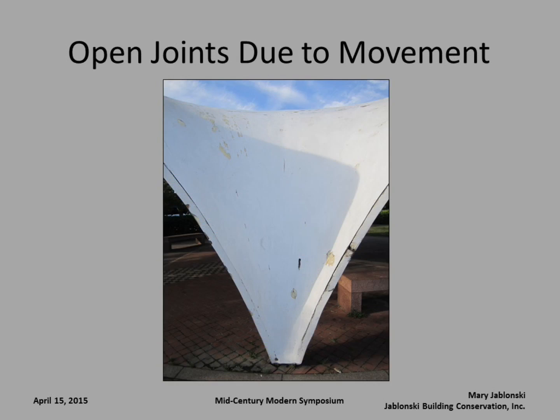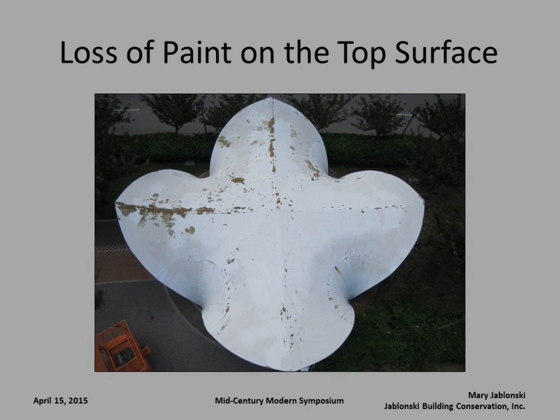Then we've also got the fact that we have embedded steel in these legs, and what happens is when these joints open and they crack due to thermal movement or wind movement, we get water infiltration, which leads to corrosion of the steel, which leads to widening of the crack joints, and on and on and on. You can see that there's significant paint loss at the top of the pavilions, and because it sits on the gel coat, this matters. This is what's protecting the fiber mat. Now, what's interesting is the fiberglass bloom on these pavilions is not actually particularly bad, and I think it's because what they did was they embedded the mat into a resin quite thoroughly.